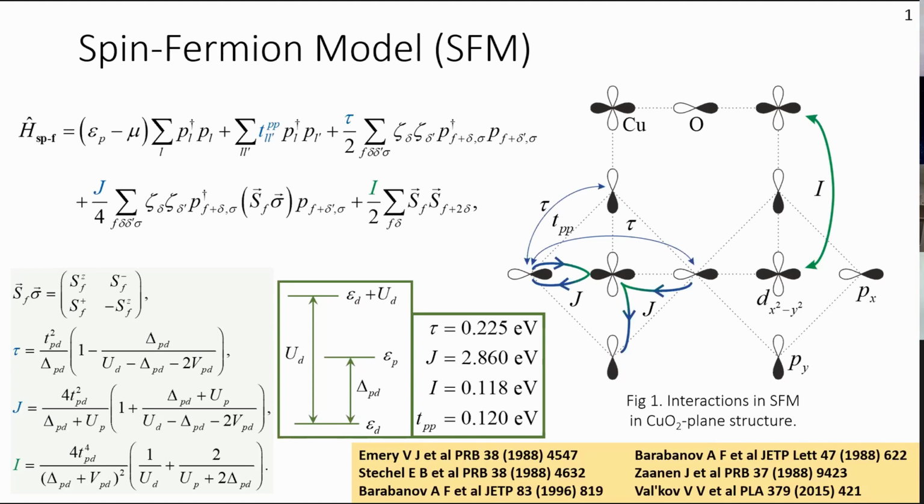In this case, the parameter J of the Spin-Fermion interactions turns out to be the largest parameter of the model. Its large value formed the basis of the concept of a spin-Fermion quasiparticle and the Cooper pair of such quasiparticles, induced by the exchange between two localized spins, as a mechanism of high-temperature superconductivity of cuprates.